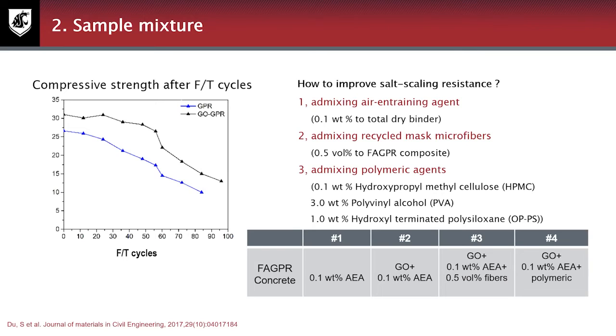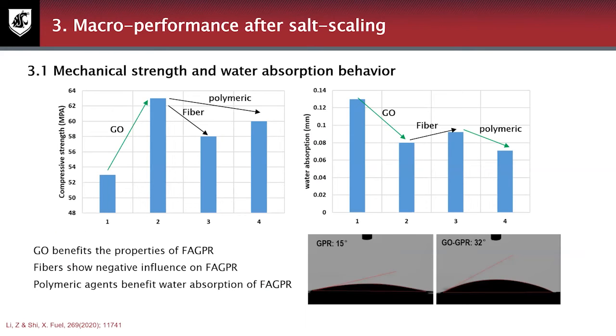Based on these 3 strategies, we fabricated 4 geopolymer concretes. The first one is the concrete containing only air entraining agent. The second one contains both graphene oxide and air entraining agent. The third one and the fourth one contain fibers and polymeric agents, respectively. And before the salt scaling, we tested the strength and the water absorption of these 4 concrete samples.